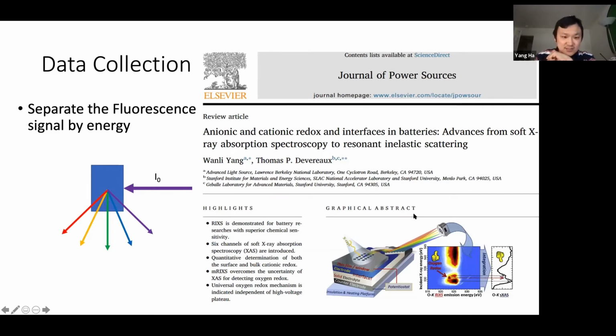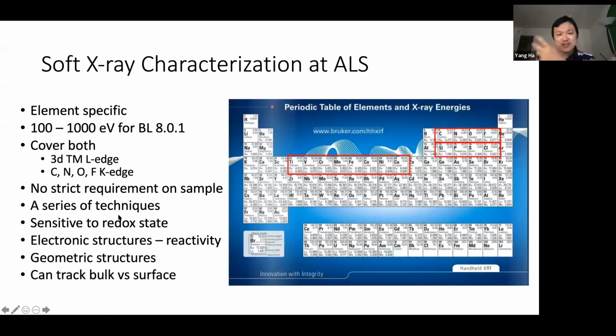So yeah, what's more, the X-ray absorption is sensitive to the redox state. As I mentioned, it is very important in batteries. And the soft X-ray is sensitive to electronic structures, which is highly correlated with the reactivities. And even though soft X-rays is not good at obtaining geometric structures, I will share one example where we can still obtain some information about the geometry indirectly. And of course, as I mentioned, we can track both bulk and the surface using the fluorescence method versus the electron yield.